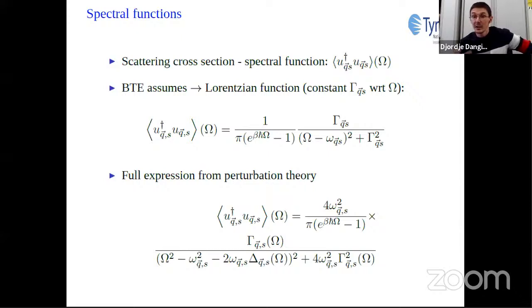The other part of the question is whether the fourth order anharmonicity is the reason why our results are so different from the experimental one in the cubic phase. I'm not sure if that's true. We calculated the fourth order anharmonic force constants, but we found that they, in the lowest approximation, do not have a large influence on the phonon spectral functions. So it's either that the lowest approximation is not sufficient in this material, or the fourth order anharmonicity is not relevant. So it's inconclusive. We don't have a conclusive answer to that question, but it is a very good question and worth exploring further. Okay, thank you.